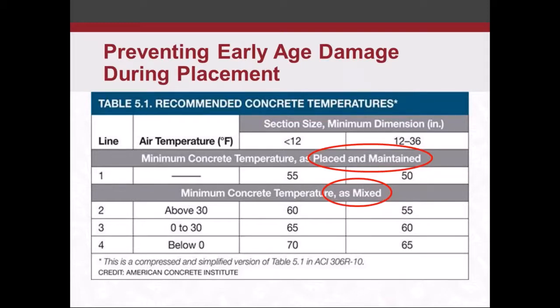So this is a table out of ACI 306. It's table 5.1 from 306-10, but I think in 2016 they did reorganize some of the chapters in 306. So I think this might be in the new ACI 306. It might be 7.1, and it's kind of a condensed version of this table. But what we see here is it's got recommended temperatures. And again, remember, this is the guidance document. This isn't the specification. So these are just recommended temperatures, although these temperatures are pretty consistent in 306.1 specifications. But we can see that depending on our section size, the minimum section size, in this case, less than 12 inches. So this would be like, say, a 6-inch slab, maybe an 8-inch retaining wall or something like that.